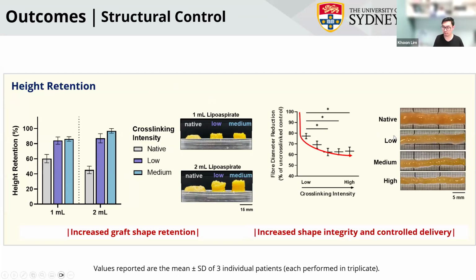What we also found is that if you play around with the cross-linking density, because you have better control over it as well, you can now better extrude it. So native fat, if you try to just push it off a nozzle, it kind of just collapses. If you have a little bit of photo cross-linking, this covalent dityrosine bond within them happening, you see better control over the fiber diameter. So you increase the shape integrity. And this is important because a lot of the problems that these patients have is if you take their native fat, unmodified, unprocessed, injected back to them, what normally happens is the fat themselves will form these globules where the vascular supply cannot get into them, and then the injected fat will sort of just die off. It will be reabsorbed back into the patient, and then the patients have to go back to the clinic for a second injection.